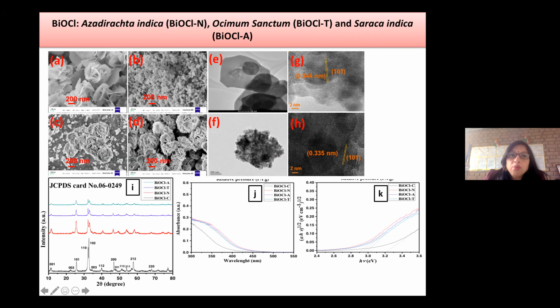To see the results, we move ahead to different characterization and different photocatalysis processes. By TEM, HRTEM, we found the lattice fringes, and they show this is BiOCl. By the JCPDS card, the XRD characterization took place, and you can see in the case of the green one, these peaks were broader. So this shows the nanoplates. The XRD also proved that it is nano, as did SEM and TEM. And when we checked its band gap, it was smaller than the hydrolysis method BiOCl. So this is the chemical BiOCl, and then it was going towards a larger wavelength.